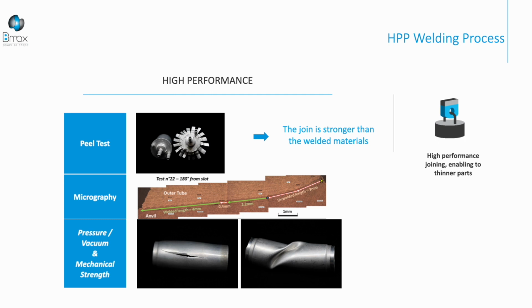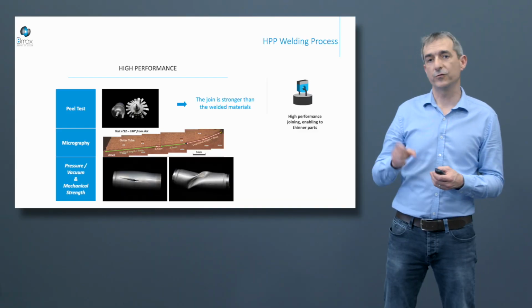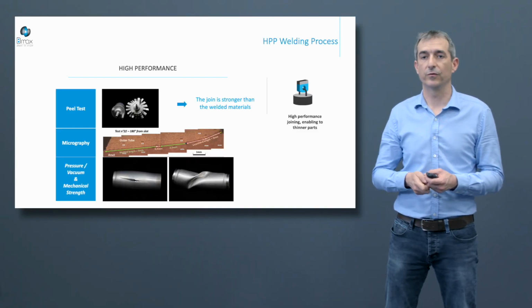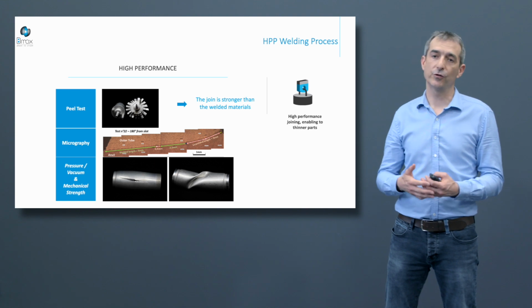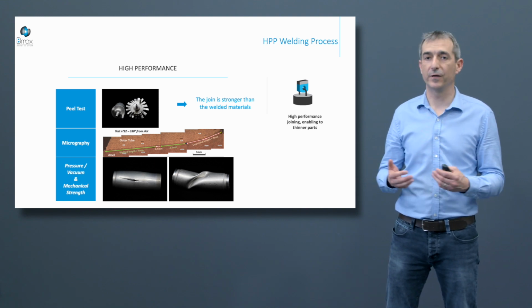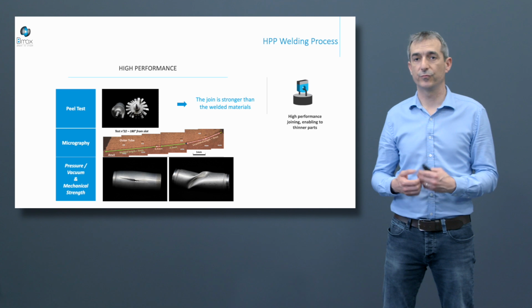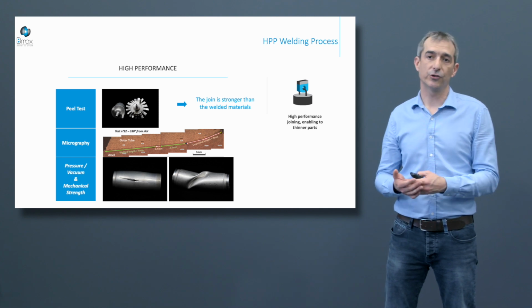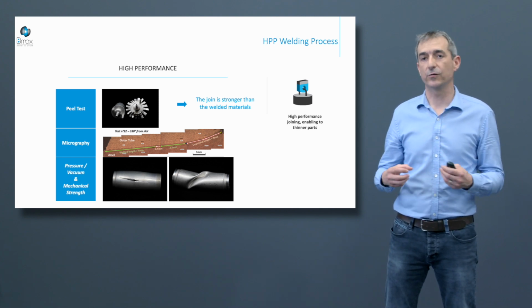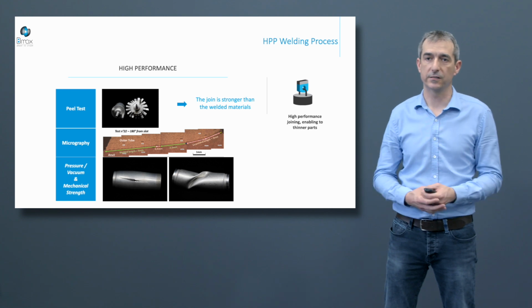For example, we perform peel test and micrography. Micrography is after the peel test. Peel test is to localize the welding and to test the strength of the joint. Micrography is to measure the welded zone, for example. After, according to the functional requirement from the customer, we can perform any mechanical test: burst test, pressure, and helium, hydrogen leakage, for example, or mechanical test like torque or tensile test.